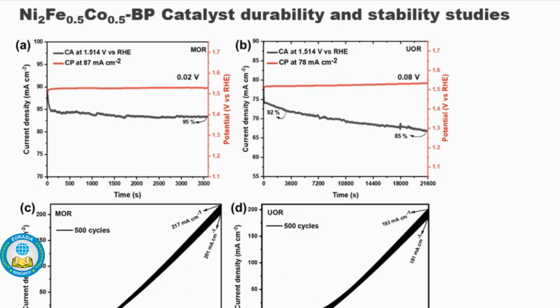The same test was done for urea oxidation reaction, and after 6 hours of the CA test, the catalyst retained a current density of about 66.5 milliamperes, which is 85% of its initial current. And CP also showed that to maintain the current density of 78 milliamperes for urea oxidation reaction for 6 hours, an additional potential of about 0.08 volts is required. And then 500 CV cycles were also conducted to study the stability of the catalyst. As you can see, for both MOR and UOR, the catalyst shows remarkable stability.